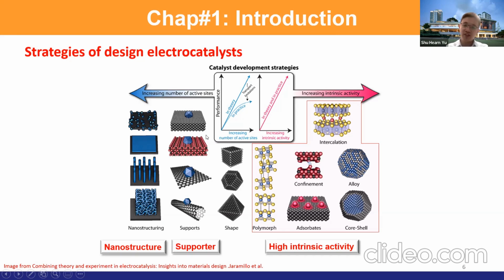So the problem here is that we cannot always increase the number of active sites as we want, because as we do nanostructuring, theoretically we increase the number of active sites, but at the same time the stability of the material will be compromised. For bulk material, the structure is well crystalline. However, when you nanostructure the material, it becomes more and more amorphous. So the stability will be compromised.